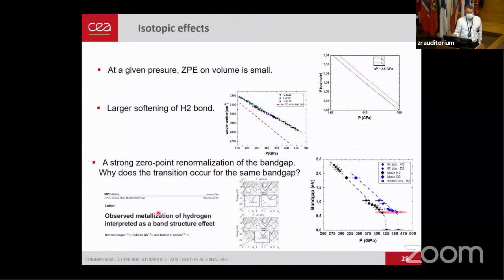So if we summarize the isotopic effect on hydrogen metallization, there is a small effect on density. In fact, hydrogen at a given pressure, with higher zero-point motion, should have a slightly higher volume, which doesn't go in the direction of lower metallization. You have a softening of the bond, as I said, as you see on normalization of the vibron.